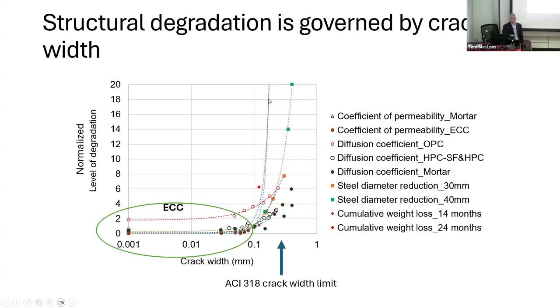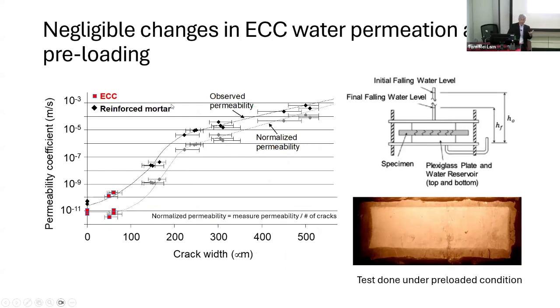So the reason why I'm showing you this chart here is that in ECC, and you saw that a moment ago in the test curves, the crack widths are intrinsically controlled to less than 100 microns. The stress strain curves, the stress crack width curves are all showing less than 100 microns, 60 microns. So it's in this range. This is intrinsic in ECC. You don't have to count on steel reinforcement in order to achieve high durability.